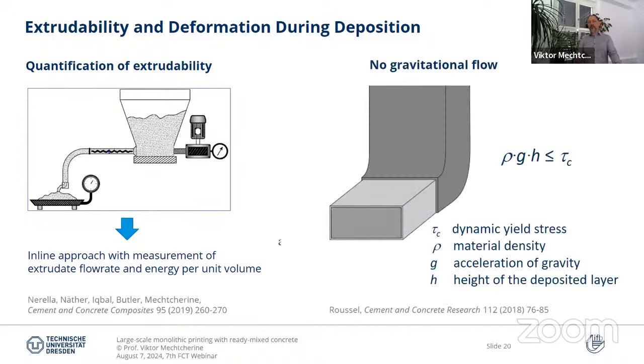And then after the deposition, if you want to keep the shape of the nozzle, we suggest to use this kind of horizontal deposition, with some knee in the nozzle, so it helps. And then you can use this very simple analytical formula to predict when the material will flow or not. So here, tau is the dynamic yield stress of the concrete, which can be measured using rheological tools, so rheometry. And then other parameters on the left are material density, acceleration of gravity, and the height of the deposit layer. So if the material is a little bit soft to keep the shape, it just flows until h is small enough that this equation works, and then the flow stops.